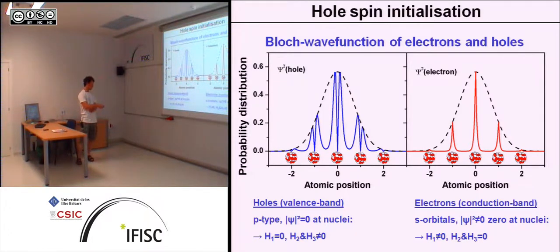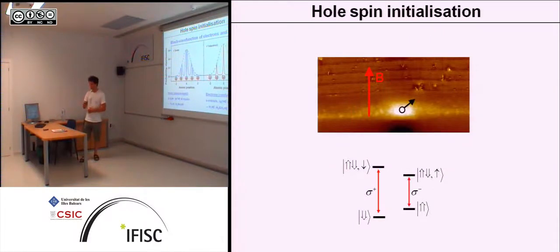So first, for holes, because we have a zero at the position of the nuclei, the first interaction term, this delta term, is zero. But because we have this spatial asymmetry, H2 is not zero. And because it's a p state with L plus or minus, we have spin-orbit coupling. With electrons, however, you have the maximum probability at the position of the nuclei. That means the first term is not zero, but the second term and the third term are zero, because first it's an s state, so it doesn't have any spatial dependency or orientation dependency, and you don't have orbital momentum, that's why the third term is zero. And this now leads to very different physics between electrons and holes.